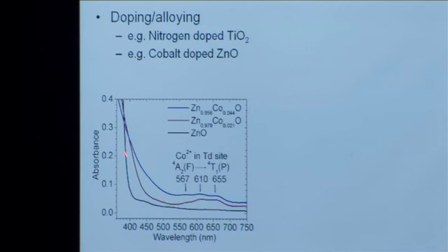Here's some data. Here's a UV-vis absorption spectrum. You can see pure zinc oxide in here doesn't absorb until you get to 400 nanometers, which is UV light, and then it absorbs light extremely well. By incorporating cobalt into the lattice, you can actually shift the onset of absorption. You can redshift it so that you're absorbing more of the solar spectrum. So that approach has certainly been shown to work in terms of absorption.